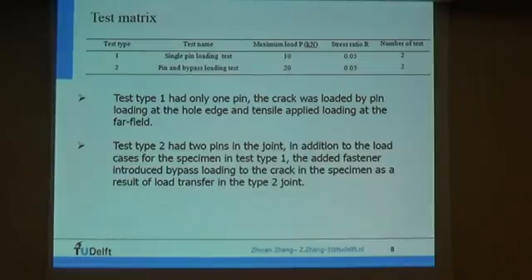Test type 1 is called the single pin loading test, and the maximum load is 10 kN. And for test type 2, we call it the pin and bypass loading test. In addition to the load case of the specimen in test type 1, the extra fastener introduced bypass loading to the crack in the specimen as a result of the load transfer in test type 2.